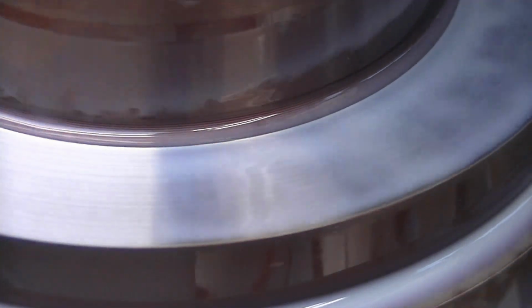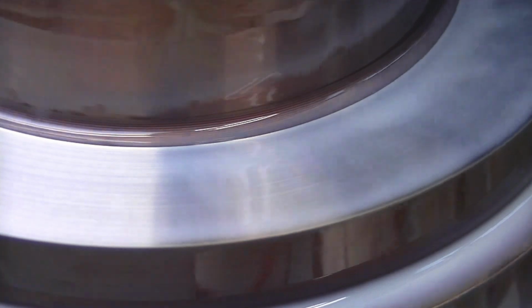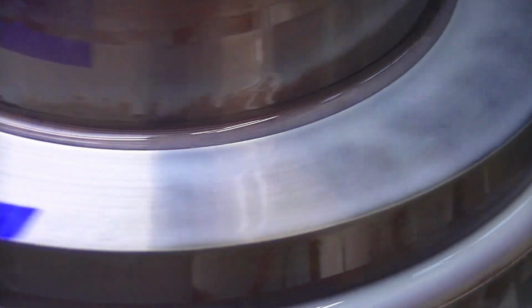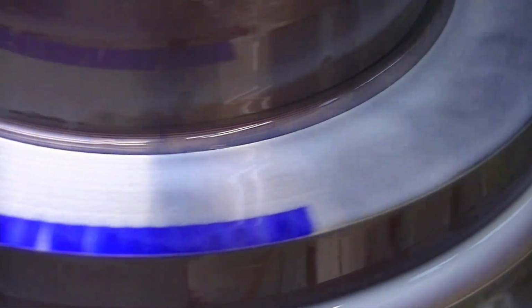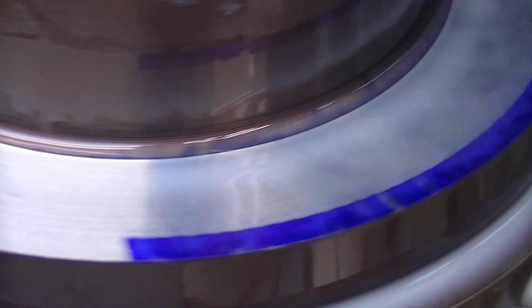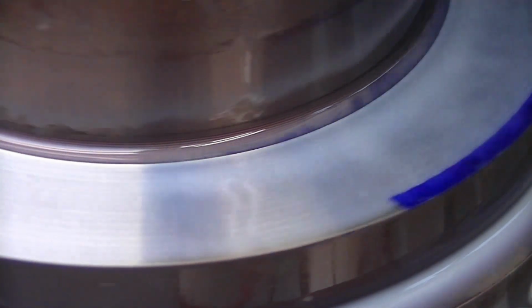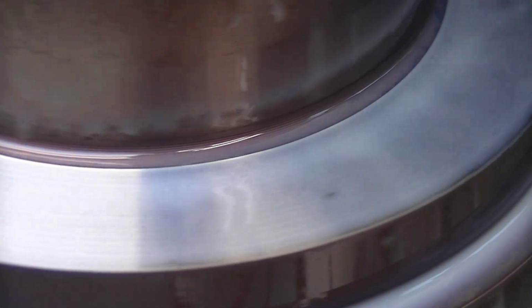Here you can see the purple Sharpie has been removed by the wheel touching down, and it's barely touching. It's maybe 10-15 millionths that is taking off there, but it's enough to remove the Sharpie, and you can see each revolution as the wheel's moving out, it's cleaning off that Sharpie. That's how I can tell if I'm actually down feeding and touching the part while the grinder's still warming up and the column's moving.